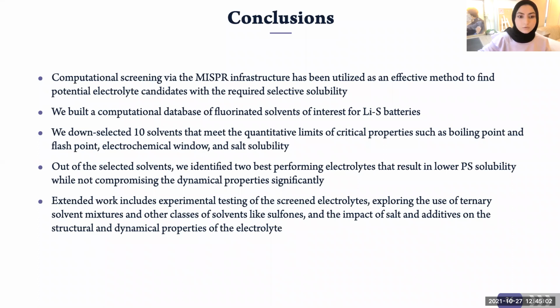So with that, I would like to conclude that in this work, we performed computational screening using the MISPR infrastructure. And we found that our method is an effective tool to identify potential electrolyte candidates that achieve the required selective solubility, meaning high solubility towards the salt and low solubility towards the polysulfide. We built a computational database for the fluorinated solvents of interest for lithium-sulfur batteries. We down-selected 10 solvents that meet the quantitative limits of critical properties like boiling point, electrochemical window, salt solubility, and so on. And out of the selected solvents, we identified some promising candidates that result in low polysulfide solubility while not compromising the dynamical properties significantly.